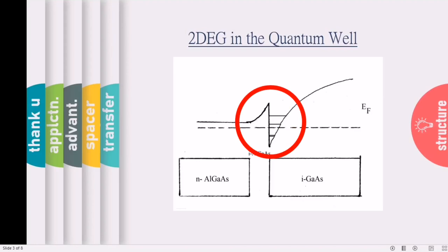The width of two-dimensional electron gas is about 8 to 10 nanometer. And these trapped electrons in the well have better conductivity because the effective mass of electron in gallium arsenide is on the lower side. And hence the mobility will be very high. In the well, we can see the subbands. The trapped electrons in the well will first occupy these low energy levels. And these subbands will be completely filled. And after that, the higher energy levels will be filled.